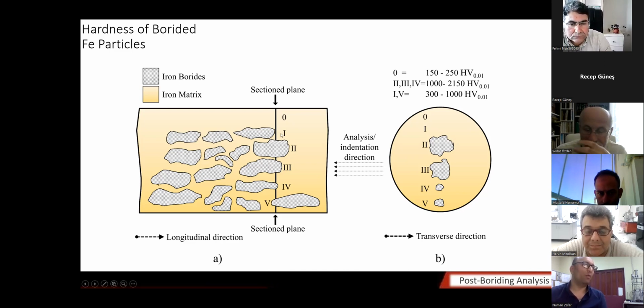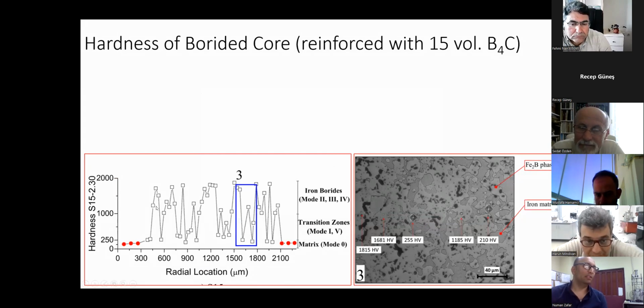And 5 and 1 might have a similar hardness because although it appears to be an iron boride, it is embedded in a very soft iron matrix. That is why it might show a lower hardness than expected. This explains why we have also witnessed these hardness values, which are not low enough to be called iron matrix and also not high enough to be called iron boride phases.